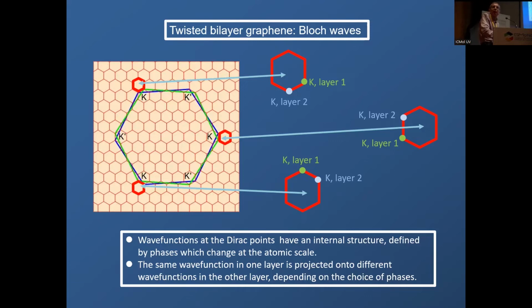Even if momentum is conserved and so on, it turns out, if you make the calculations right, that this initial plane wave becomes a superposition of 3 plane waves when it tunnels into the second layer. Then it tunnels back to the first layer and it becomes 9 plane waves. So the system rapidly becomes very complex, and it's even more so the smaller the twist angle is. And this complex interference process is what is responsible for this large change in the spectrum of the system. And these are the so-called magic angles.